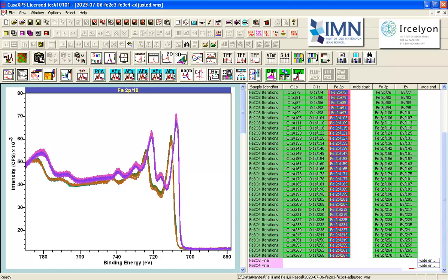And the answer is that these two samples were measured assuming that they were insulating materials, and both were measured using charge compensation. And in this instance, the charge compensation is low energy electrons that are returning to the sample surface by a filament mechanism. And these low energy electrons are having a profound influence on one, that is to say the Fe2O3, and almost no influence on the Fe3O4.